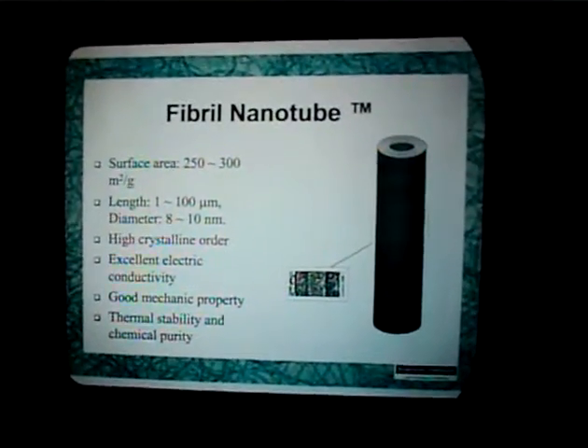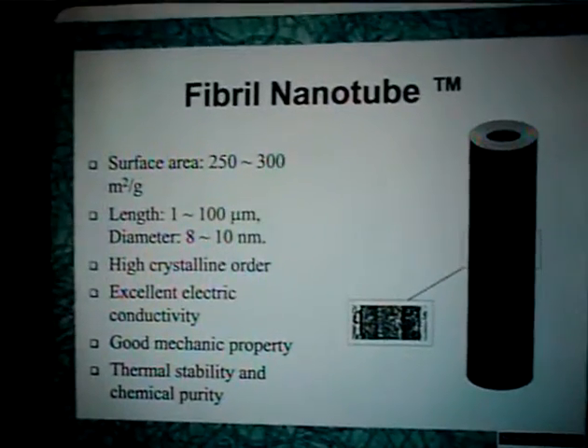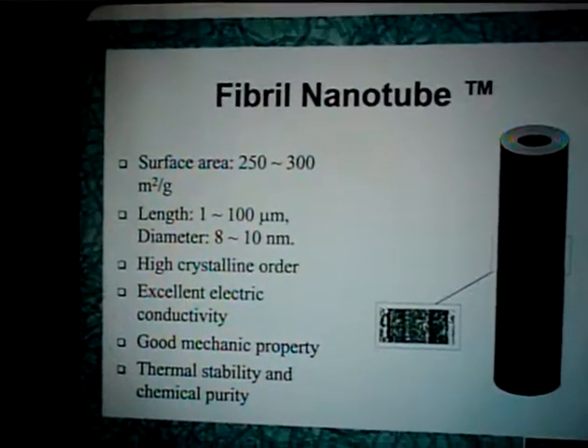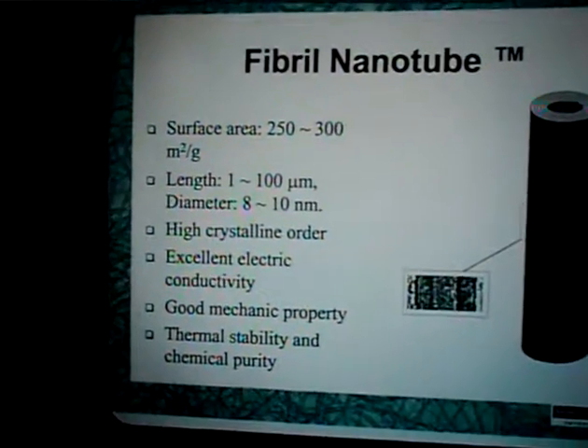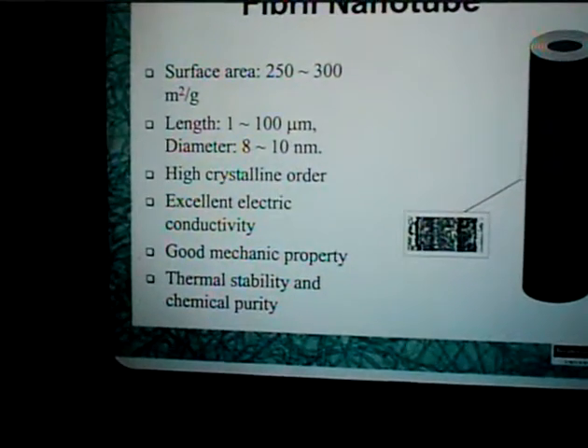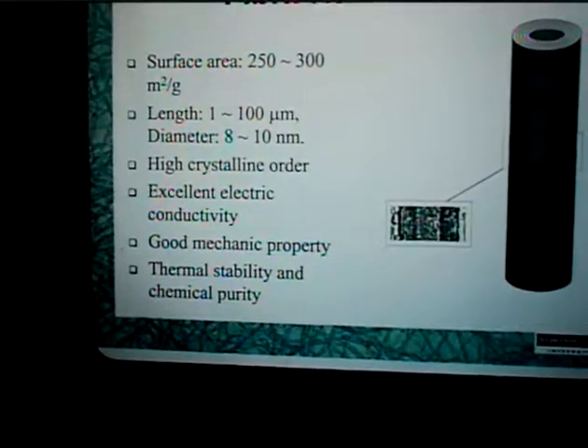It has a length of 1 to 100 microns. It's very large. The amount of catalyst that's there is very minimal. It looks very much like the polymer that you use, for instance, to make polyethylene. It's a very small amount, and this thing grows out of the catalyst. Diameter 8 to 10 nanometers. Looking at this, you may think it's a long, large tube that's hollow inside. That's not the idea. You see in the TEM later on, it has many defects. And in fact, those defects are very important for the mechanical and chemical properties of this material.